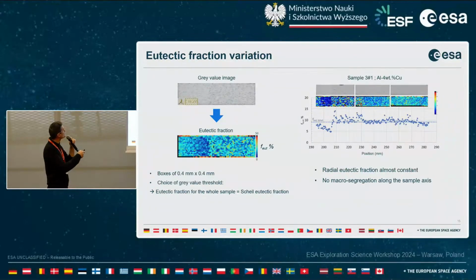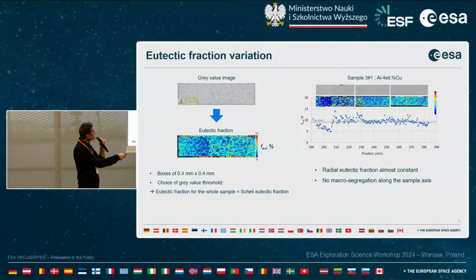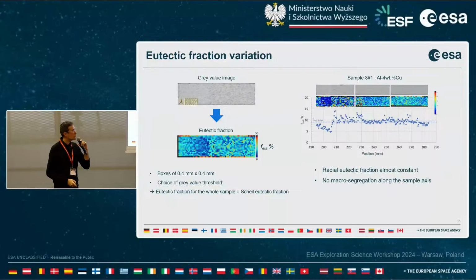And what was done also at Access was to measure an important parameter, which is the eutectic fraction, because maybe you can see on the picture that there are areas that are white, areas that are dark gray. So white corresponds to the aluminum and dark gray corresponds to the eutectic phase. And by taking some small boxes and characterizing the fraction of this black and white region, we can deduce the eutectic fraction. And if we plot this eutectic fraction along the sample, and we collect the radial eutectic fraction, we can see that it is almost constant along the sample, except here, but here it is the initial seed, since the sample was partially melted.